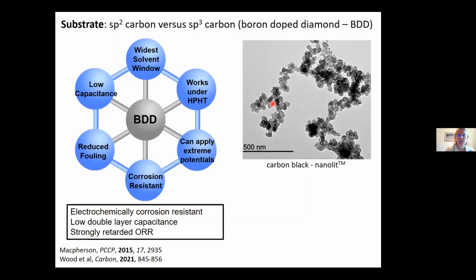For those of you that know me, I've been working with boron doped diamond as an electrode material for many, many years now. And boron doped diamond has many advantages. It really does give you a very low capacitance. You get beautiful electrochemical cyclic voltammograms and responses. It has a wide solvent window in aqueous solution because electrocatalytic processes are really slowed down on boron doped diamond. And if you get very high quality BDD, you can really push out the oxygen reduction wave to a point where you can't even really see it in the aqueous solvent window.